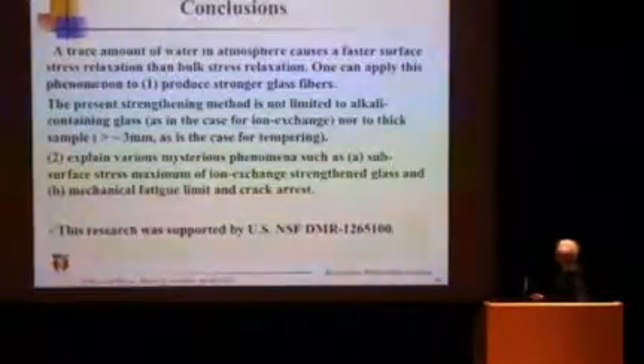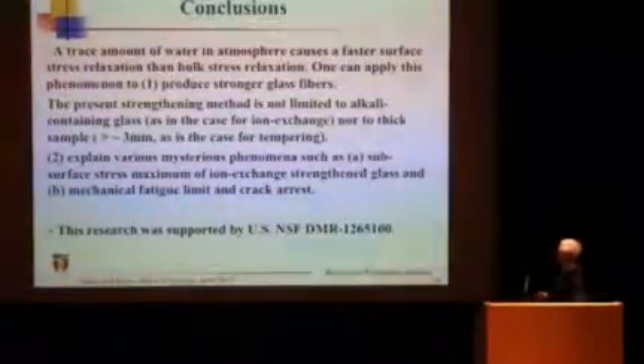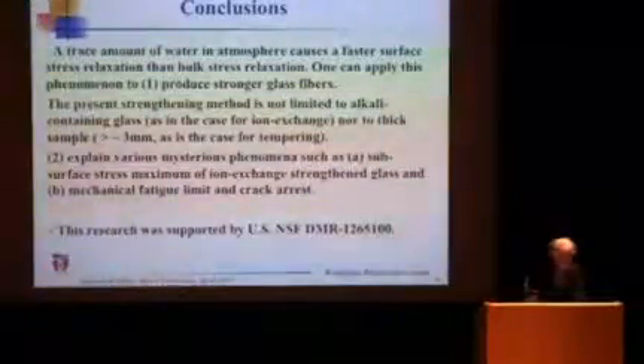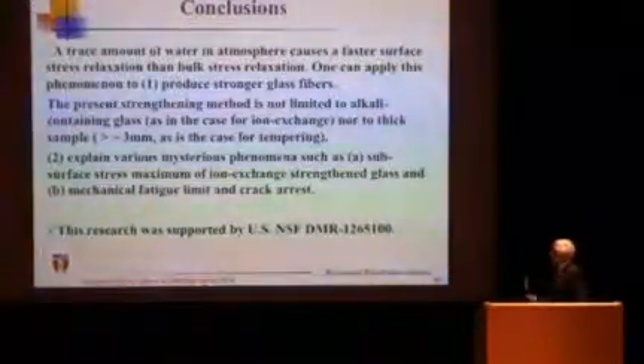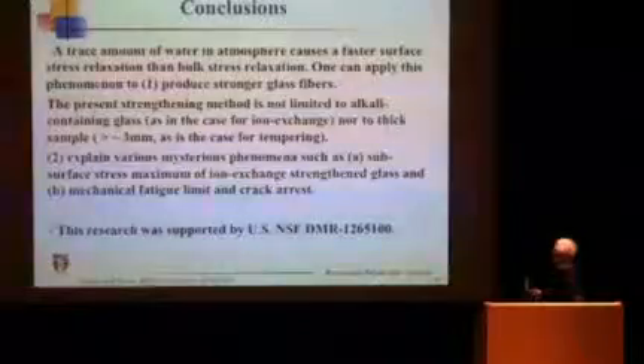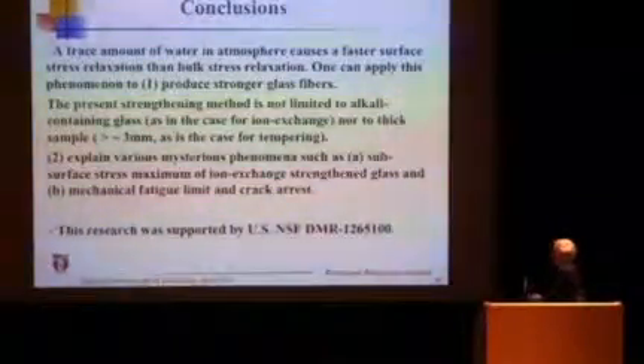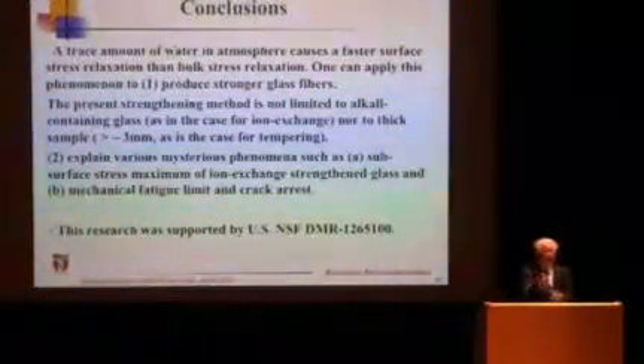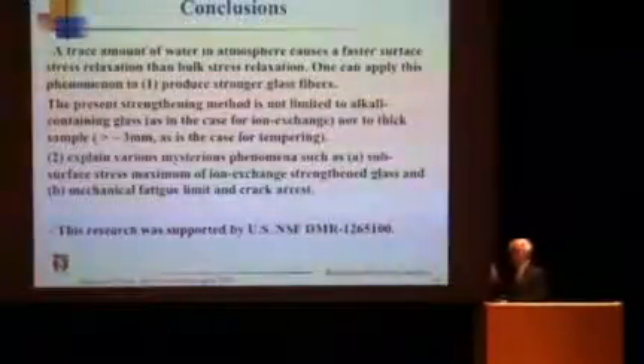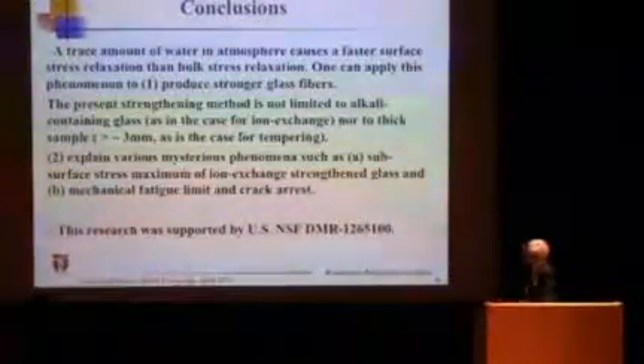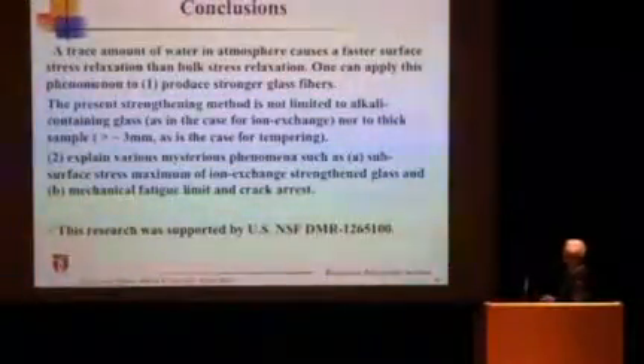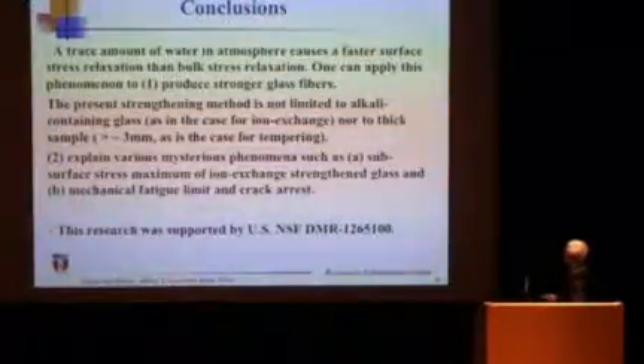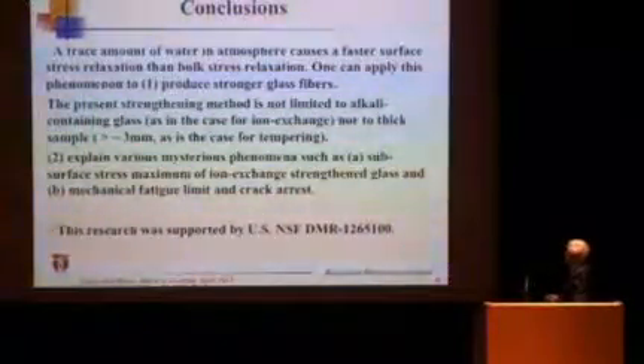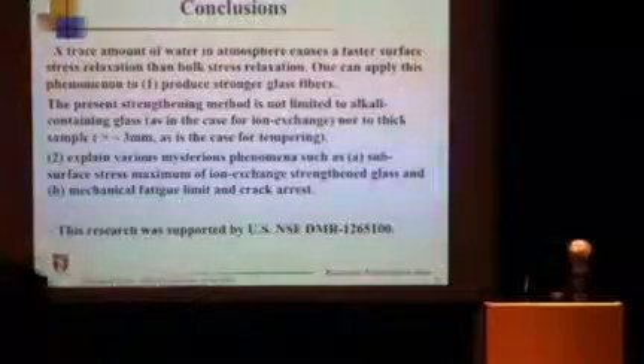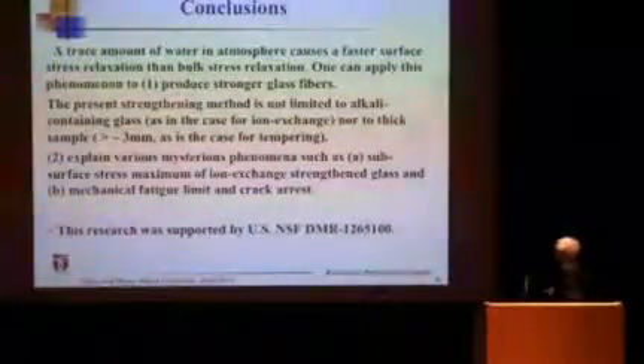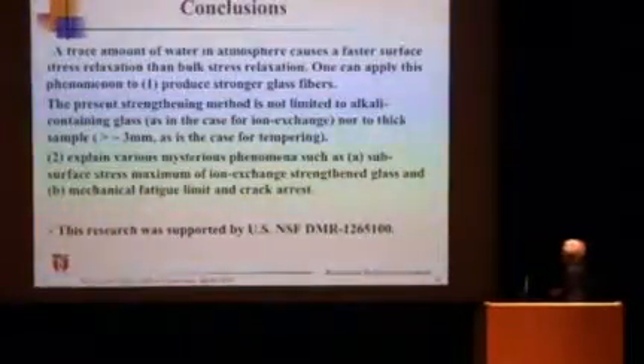Finite thickness is not needed, just like in tempering, and we don't need ions for ion exchange. Any oxide glass can be strengthened by this method. Even if you have a large bar, as long as you have enough machine to pull, you can make the glass stronger. At the same time, this method, faster surface stress relaxation, can explain various mysteries known in the glass science community.